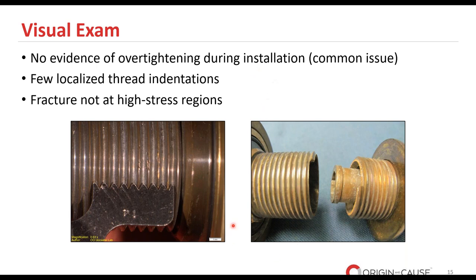Looking more closely, we did notice a few localized thread indentations. These marks could potentially indicate points of stress or strain on a component, warranting a little bit more exploration. And looking at the fracture's location here, it wasn't located in an area that we typically consider high stress. And this points toward a more unconventional cause and emphasizes the need for a deeper dive beyond just surface level observations. So taken together, these visual cues can provide an initial direction which guides the subsequent phases of our investigation.